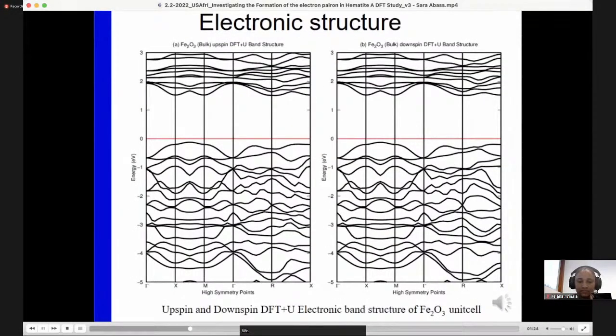We have looked at the electronic structure of hematite. It is an antiferromagnetic material. We look at the band structure at the majority spin and minority spin, which was used to produce a band gap. In this case, there is a gap in both the up spin and down spin band structure. For this material, the band gap agrees with the previous literature.